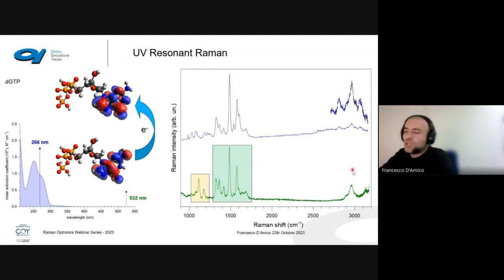Here we have the CH vibrations, basically, and here we have a tail that starts to rise due to the water contribution, because this spectrum has been collected also in a water environment. The same region instead, in the resonant spectrum, has a completely different line shape, which contains the same peak and further peaks that rise, which are due to overtone vibrations. All overtone vibrations could also be present in the spontaneous spectra, but are enhanced when we have an electronic transition and resonant Raman effects, basically.